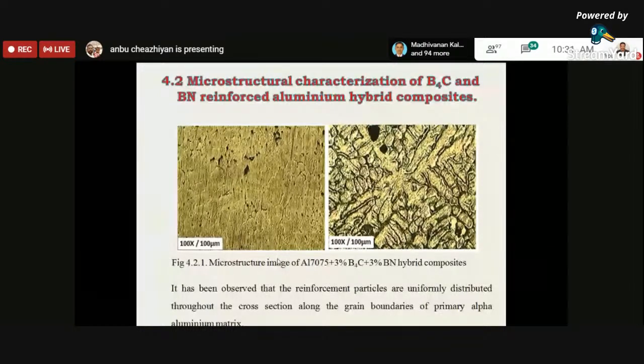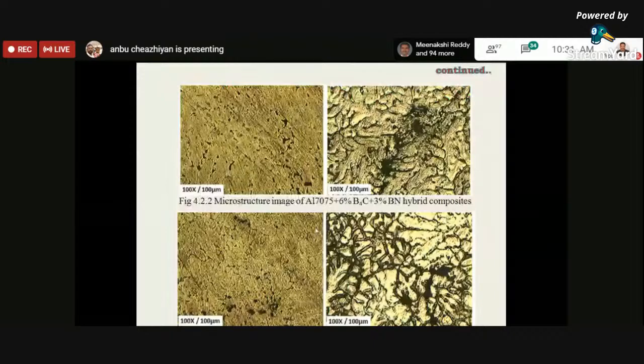From the microstructure, it has been shown the reinforcement particles are uniformly distributed throughout the matrix without indication of clusters. But in the case of 6% boron carbide, we can see some clusters around the regions of grain boundaries, the aluminum grain boundaries. So it is clearly evident that with the increase in temperature of the molten metal, the reinforcement particles cannot be dissolved to the maximum, and hence it appears as a fine globular species in some regions of the matrix alloy.